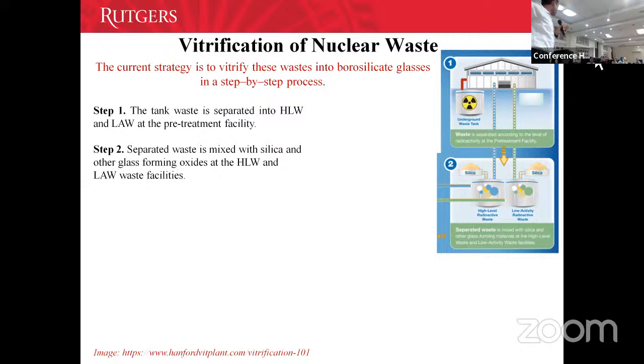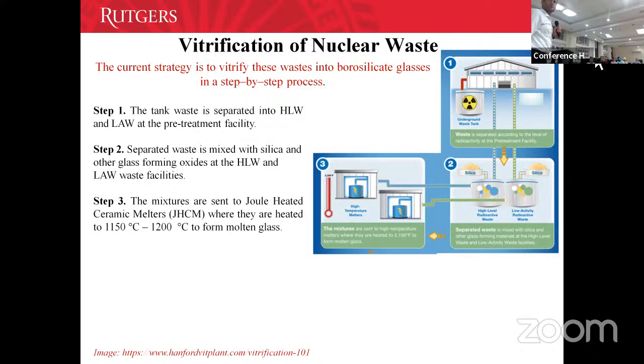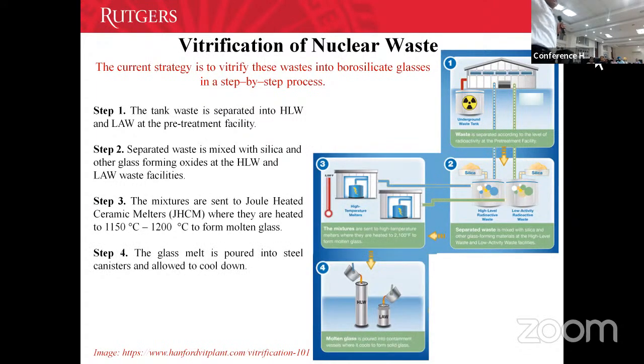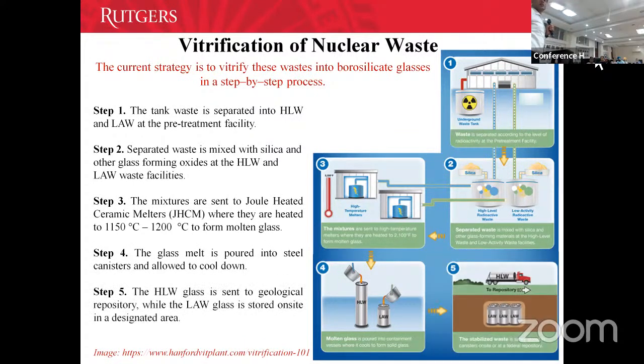The melters are huge. And this waste is mixed with components like sand, silica, and calcium oxide, like your limestone, for example, sand, limestone, boric acid. They mix it with these components and then melt it at around 1150 to 1200 degrees C to convert it into glass. And then this melt is poured into steel canisters and shipped to a repository, wherever it has to be stored. High level waste will go to some geological repository.